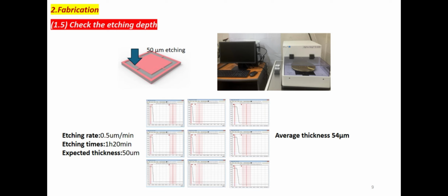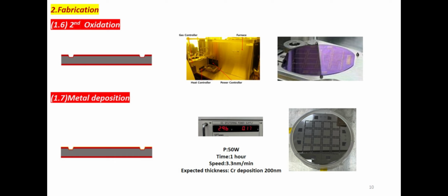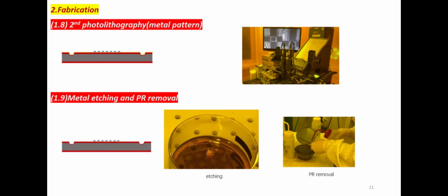The expected thickness was 50 micron, and the surface profile shows that the thickness was basically 50 micron, which is close to the expected result. Next, the second oxidation is performed, and then the metal deposition on the front is performed. We set the parameters according to the deposition rate, and the deposition thickness is about 200 nanometers. Through the second photolithography and metal etching, we get a sensor pattern.